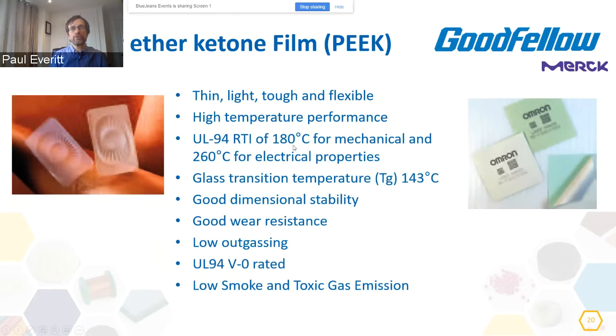It has a very high temperature performance, but not quite as high as obviously Kapton, and is rated to 180 degrees C for mechanical and 260 degrees C for electrical properties. However, bear in mind it does have a glass transition temperature of 143 degrees C. So you are seeing softening before you get to 180, which is why it's relatively flexible. The other thing to bear in mind with that glass transition temperature of 143 is that the amorphous material will actually recrystallize at around that point.